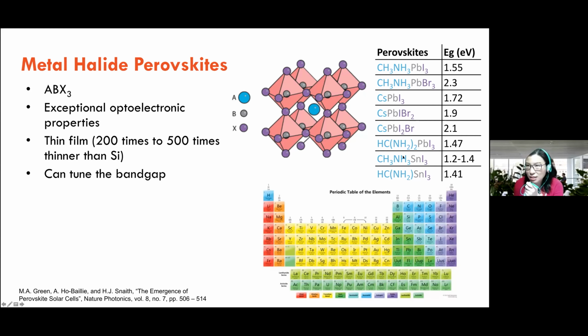So if you look at the right-hand side, you can see that by changing the A side, which can be methyl ammonium or formamidinium, I can never pronounce that properly, or cesium, we can change the band gap. We can also change the B site to lead or tin or a mixture of those, and also with iodine or bromine or a mixture of those. So basically my research group has tried almost every combination in this table. So now the state-of-the-art material is usually cesium, FAMA. Anyway, I'll show you what their stability is like.